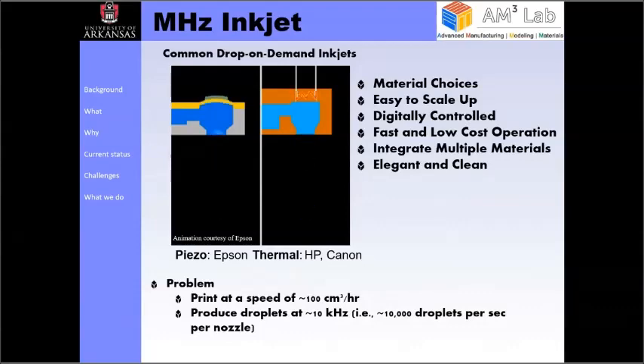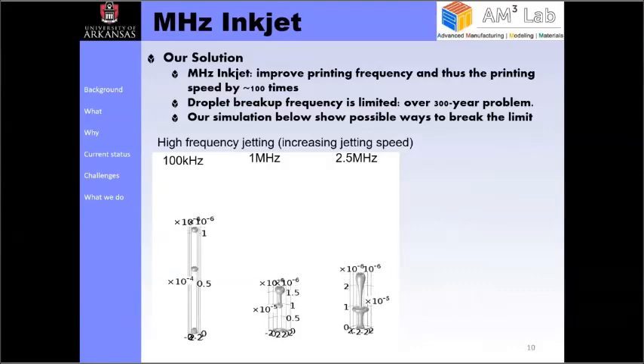It sounds like a lot, but if you do the math, you'll find the volume of droplets is not actually that good, because the droplet is very small. If you think about the 600 dpi inkjet printer, the droplet size is typically around 50 microns. So that gives a very low speed. So what we want to do is to improve this printing frequency by 100 times. We want to get to a megahertz inkjet printer. If we can do megahertz compared to 10 kilohertz, we can improve the speed by about 100 times. And this is actually a very, very challenging problem.